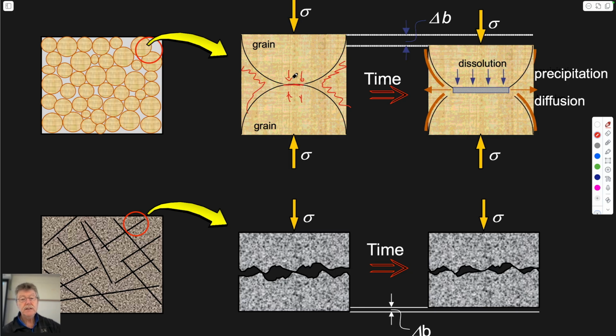So all of this stress here can only be carried on this connection. And so the stresses by just the tributary areas have to be high on this region here and 0 on this region here. So as a result of that, this patch here will preferentially dissolve, and the mechanism by which it dissolves is you get a thin monolayer of water as a solvent on this interface, and the stuff that preferentially dissolves here much faster than the pore gets transported by a concentration gradient.